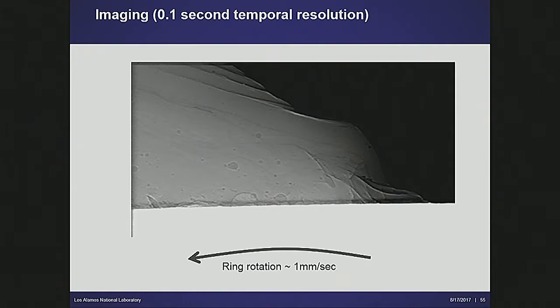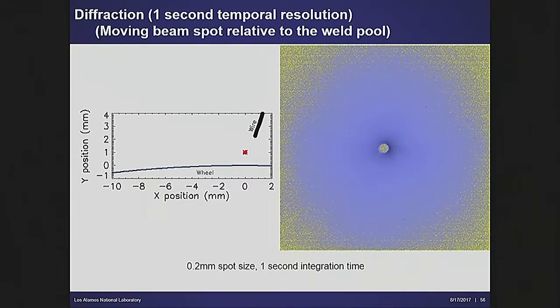The challenge for the technique is to see whether you could draw some conclusions about this porosity during the weld process. If you could see it and extract the information, you could optimize the welding parameters. So that's pretty pictures with a lot of potential, particularly if you can get better resolution and better temporal resolution. Let's turn to diffraction, where it's a little bit easier to see something quantifiable immediately.